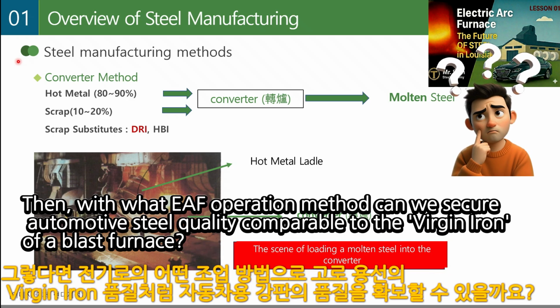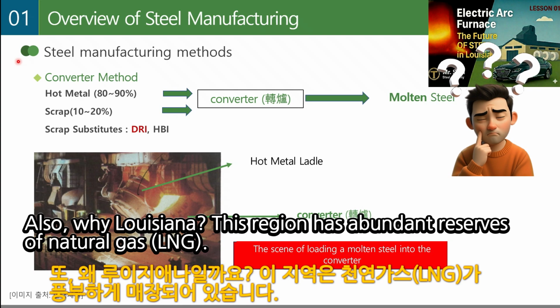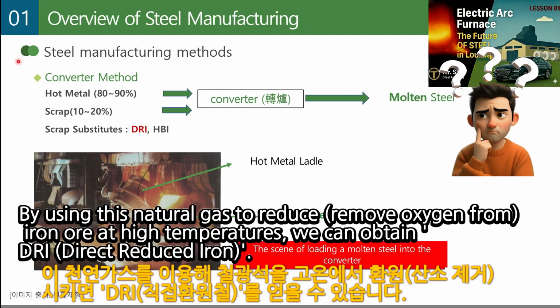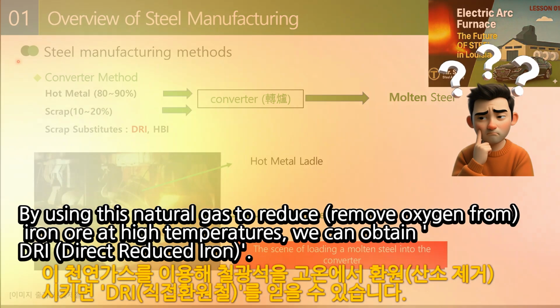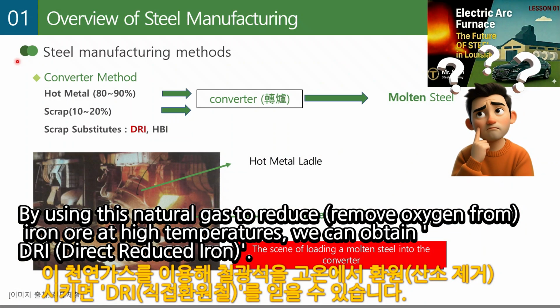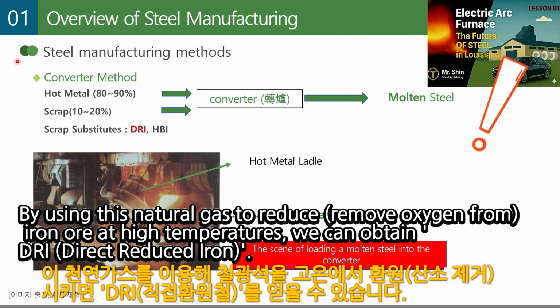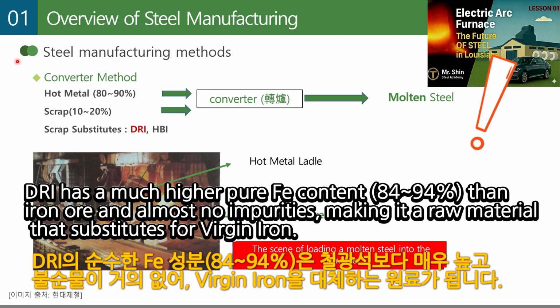Then, with what EAF operation method can we secure automotive steel quality comparable to the virgin iron of a blast furnace? Also, why Louisiana? This region has abundant reserves of natural gas, LNG. By using this natural gas to remove oxygen from iron ore at high temperatures, we can obtain DRI, direct reduced iron. DRI has a much higher pure Fe content, 84-94%, than iron ore and almost no impurities, making it a raw material that substitutes for virgin iron.